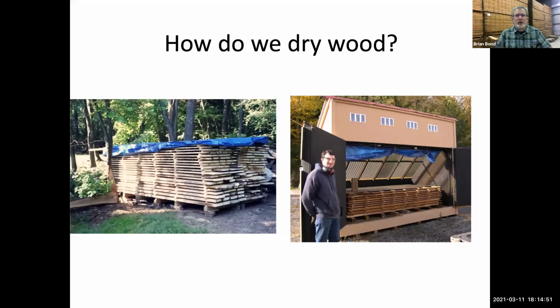So how do we dry wood? Well, you can just stick lumber out on sticks. The reason we put it on sticks is you want to get airflow on the top of the board and on the bottom of the board. And so we put lumber on sticks to get airflow on the top and bottom. You can stick that lumber out in an environment anywhere you want it to go, and it will begin to dry. So when you cut down oak, it's probably somewhere around 75%, 70% moisture content, green off the saw.